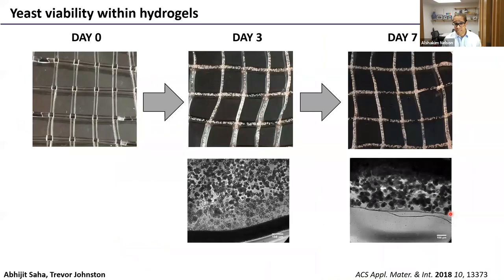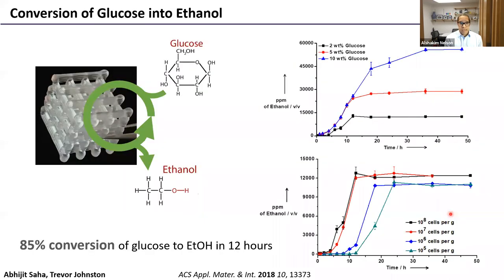Okay, so we can incorporate cells like yeast into our gels, and then we can extrude them and cure the structures. And then over time, if we submerge this in media, the cells will grow. And we can visually observe the formation of colonies within these hydrogels. Printing a multi-layered lattice construct that has these yeast, if we submerge this construct into a solution of glucose, then the yeast cells that are inside will transform that glucose into ethanol over time. And that's true whether we're changing the concentration of glucose or even the initial cell seeding within these hydrogel constructs.